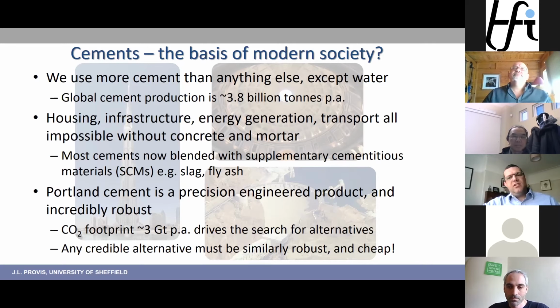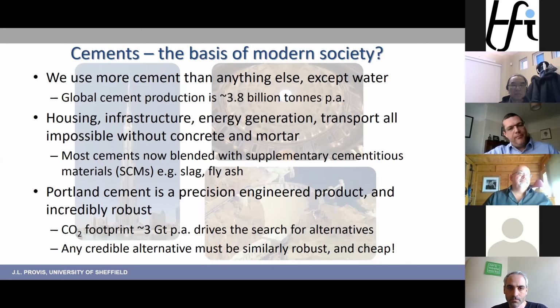We blend cement with supplementary cementitious materials very extensively. It's increasingly rare to find cements sold and used commercially that are not blended with some form of supplementary cementitious material when we're applying these in concrete. So we blend with blast furnace slag. And actually the construction sector is, in a lot of countries, paying about the same amount of money for ground granulated blast furnace slag as it does for Portland cement on a per ton basis. It's an additive that improves the performance of our material significantly.